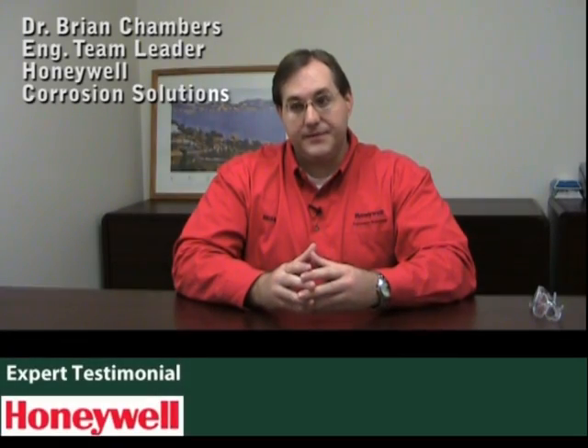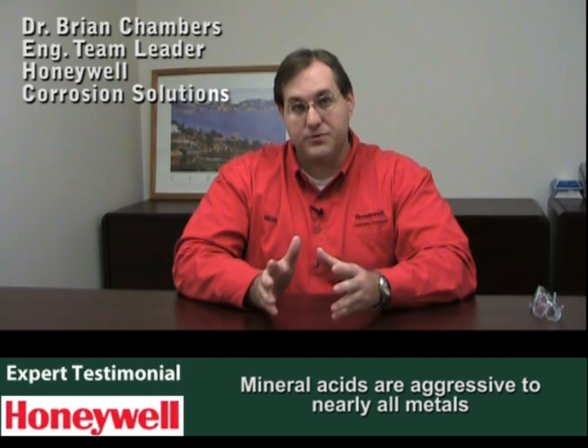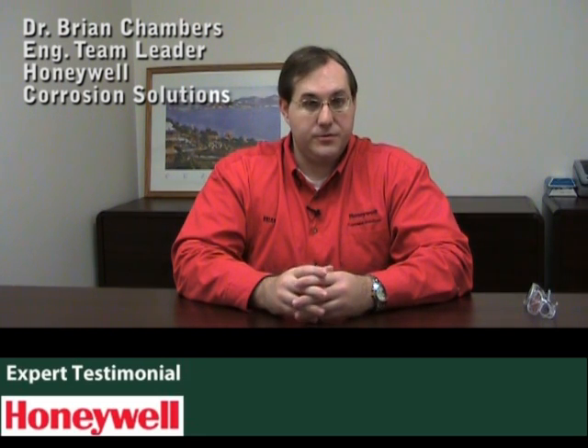The acidizing obviously comes with high corrosivity due to the mineral acids being present, which are extremely aggressive to almost all metals present in upstream production. The oil and gas industry needs to understand the implications of acidizing on the metallurgy present, because if they have a failure due to either extreme corrosion or environmental cracking, they can lose either their tools that are going down hole or the actual production tubular. The loss of either of those things can mean millions — if not larger sums of money over time — not to mention the safety implications of having to shut in the well during operation. So it's very important for them to understand how often they can do these acidizing treatments and what the implications are for the particular well materials they're using in that particular field.